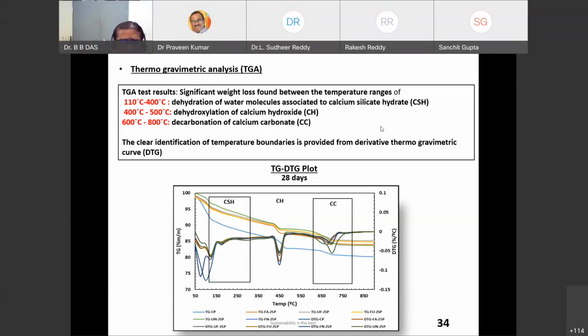All right. Now, when you go to the DTG, DTG is just this graph. DTG will show there are different phases, and the loss of water happens in different phases, or you can say different temperature boundaries. These are the three temperature boundaries. The first temperature boundary we know is 110 to 400 centigrade. There will be many actually, and you can see here it is starting a little early. That is fine, but the mass loss between 110 to 400 is meaningful to me, because it designates the calcium silicate hydrate.